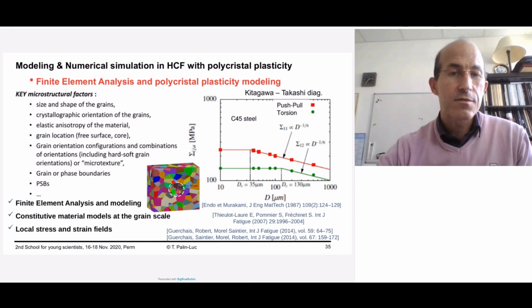or the effect of the internal of the material, the difference in stress state depending on the location of the grain, and also the phase orientation. You can imagine modeling a material with different phases, I mean with different mechanical properties, like ferrite-martensite or ferrite-pearlite, bainite, etc. So this approach is able to model the metallurgic effect or the metallographic effect on the fatigue resistance and the